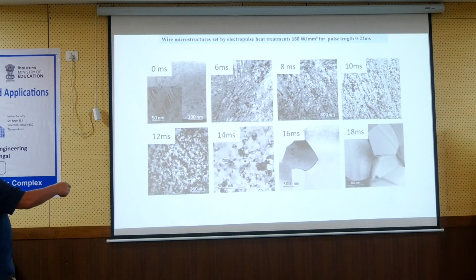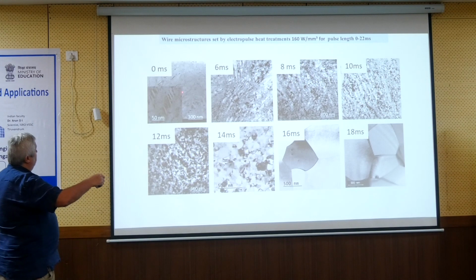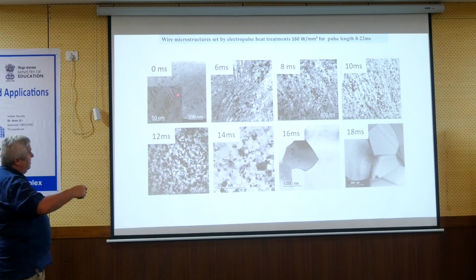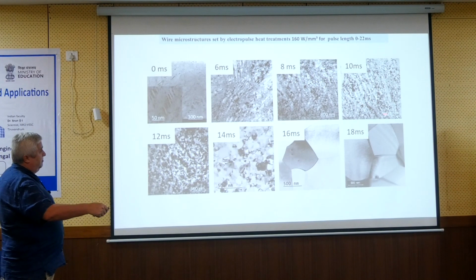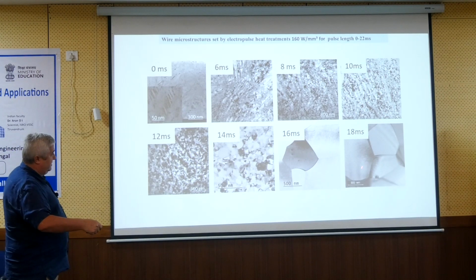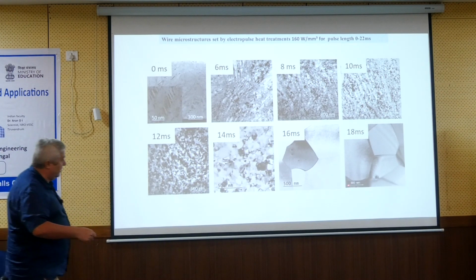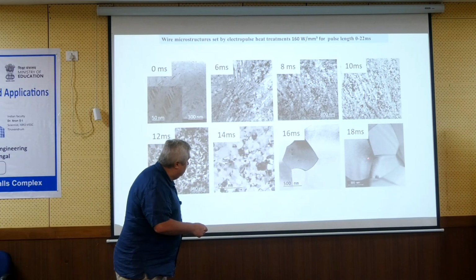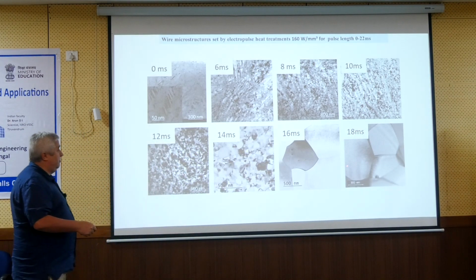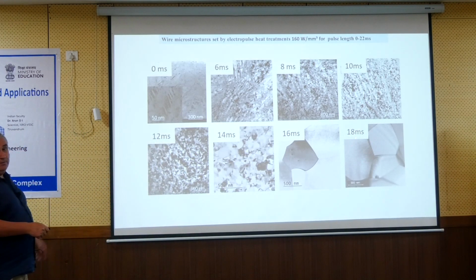When we look by electron microscopy, this is the cold work wire, and this is the maximum temperature wire with grain size of a few microns. Here it is like 1 micron, but we can go up to about 6 microns. It's not linear, yeah. So if I make 20 milliseconds here, it will be like 6 micron grain size. So these are completely different wires, very different.